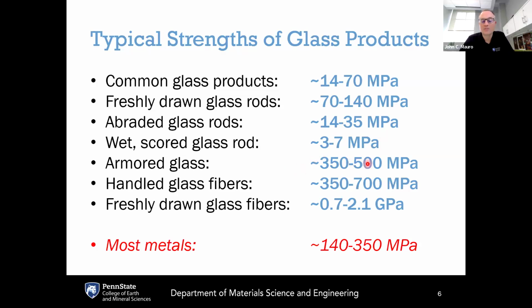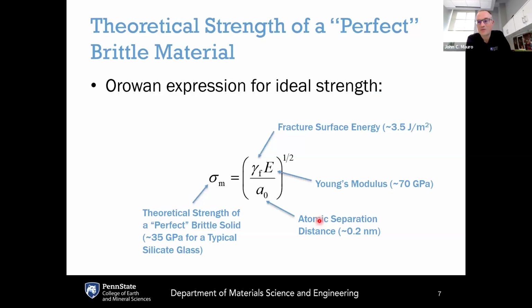Armored glass can be up to several hundred megapascals, glass fibers even higher. And if you have a freshly drawn glass fiber, it can be as high as 2 gigapascals. Now, if we compare the ranges of these numbers to typical metals, which are on the order of 140 to 350 megapascals, you see that glass is actually capable of being quite a bit stronger than most metals, but at the same time, many of the glasses that we commonly observe are actually weaker than many metals. And what is the reason for this? The reason, of course, is the existence of flaws.